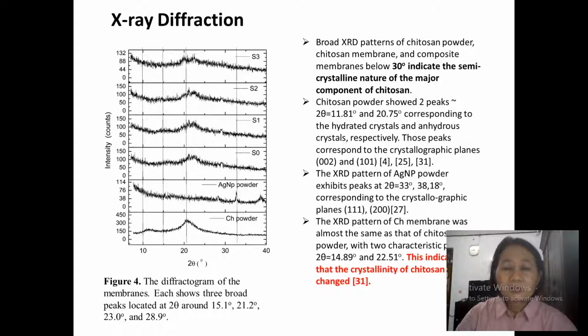Okay. This is for the X-ray diffraction, where we got the broad XRD pattern. The broad peak for the chitosan powder, chitosan membrane, and composite membrane is below 30°. This indicates the semi-crystalline nature of the major component of chitosan.